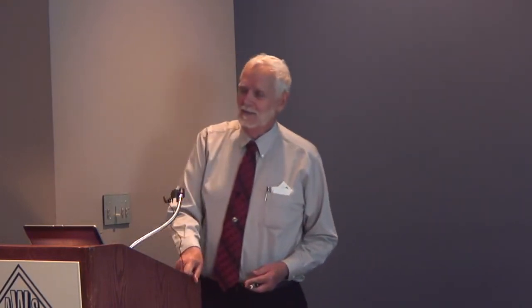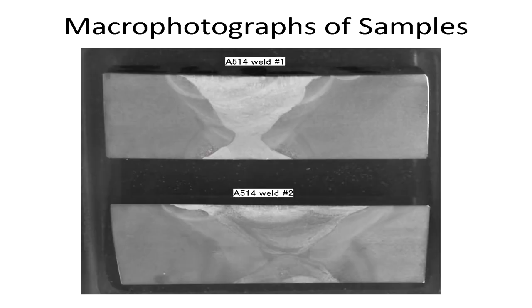And then there's something really neat that nobody will notice, but you look at it for a second. All right, there it is, right? The hardness test was taken right to the center, just like that. Now notice, see the heat affected zone here? Nice even heat affected zone. See the heat affected zone here? It's about twice the width of that. Well, I had twice the heat input. Big weld. And you can see how big and gobby this weld was. I put a 6010 root in it and had to grind it down, and big weave passes.